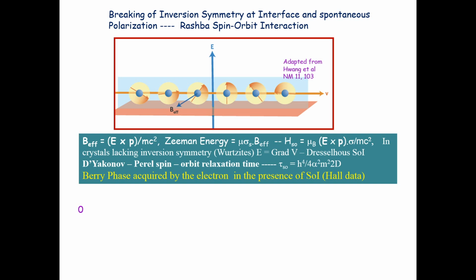The other effect of this built-in electric field is the effect on the velocity of the electron because of the Lorentz force experienced because of this field. And that induces a Berry phase. One can measure the Berry phase by doing perhaps Hall effect measurements. But the simplest way of seeing whether there is spin orbit interaction or not is to look at the transport properties at very low temperatures. If it is a diffusive 2D electron gas, there will be localization. And spin orbit interaction tries to kill that localization.